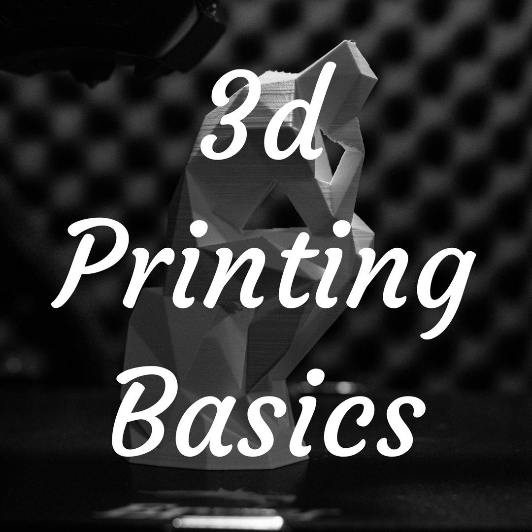If you add more walls, for example, the common setting for 3D printing is usually 2 walls on the outside. And if you change that to 3 to 6 walls, it becomes far stronger than increasing the infill from 20% to 30%, 30% to 40%. Adding more walls will make your part overall stronger.